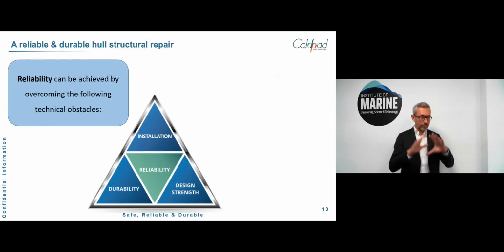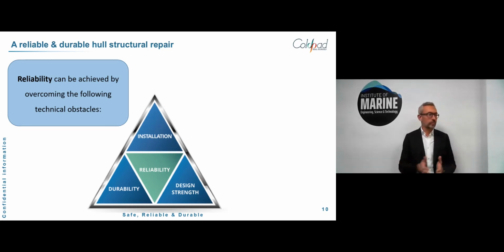So when we talk about reliability, we have conceptualized this reliability aspect for bonded connections. What is very important, what you must remember, is that bonding dislikes water. Water is one of the worst enemies of bonding in the two stages, during installation and during service life. Bonded composite reinforcement is widely used in the aerospace industry and also in the civil industry. What they usually do is work in a warehouse where they control the atmospheric parameters. Ideally, you have to reach something like 50% humidity, lab conditions. That's the best for structural bonding. When you do civil engineering work with composites, you can allow up to 70% humidity level. When you are offshore, you easily reach 90% or 100% humidity with moisture, dew point, condensation onto your substrate.